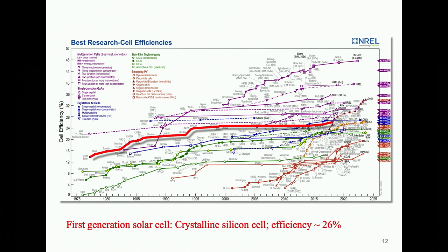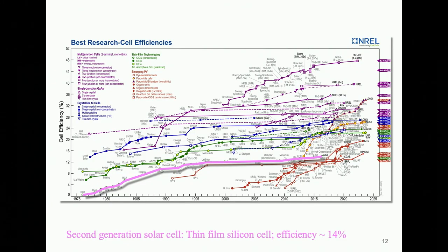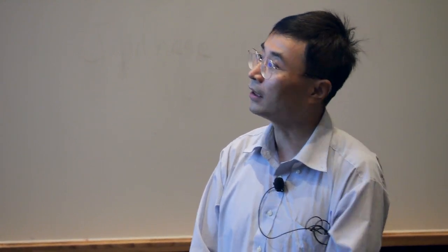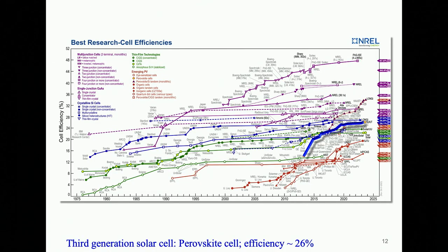So to reduce the fabrication cost, researchers have been developing the second generation of solar cell with a silicon thin film cell as the representative. Thin film silicon cell can be made at a lower cost, but it also suffers from low efficiency of about 14%, which is about half of the crystalline silicon cells. So to achieve the high efficiency and also the lower fabrication cost, the third generation of solar cells have been developed with the perovskite solar cell as its most prominent representative. Over the past decades, perovskite solar cell has been intensively studied with its record high efficiency now exceeding 26%.